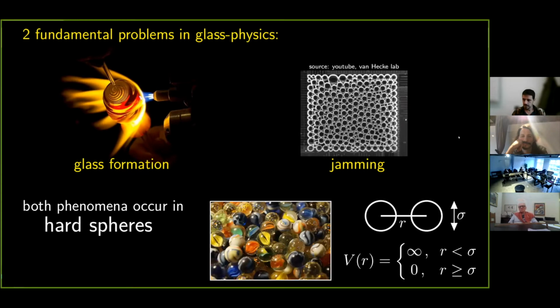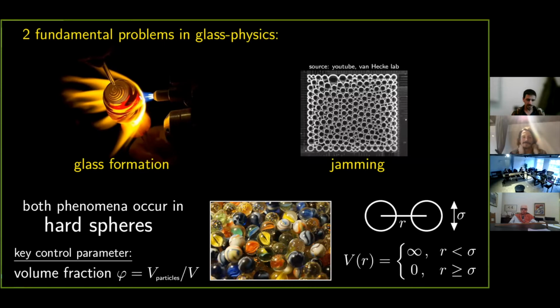And it turns out that both of these phenomena occur in the canonical hard sphere model that I am just spelling out here. What you assume is that you have hard spheres that all have the same diameter sigma, and the potential is infinite if they overlap and zero otherwise. In this system, the key control parameter is the packing fraction, which is simply the volume occupied by the particles divided by the total volume of the system.